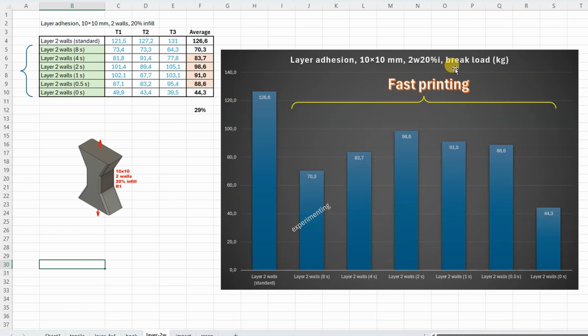Standard speed, fast printing, and I already mentioned that this 8-second version was experimental printing, playing with parameters. Now I'm not sure, only this one doesn't really fit into this picture, the 4-second version. Maybe he was still experimenting with the parameters, I'm not sure, but after this more or less constant values, and only here I could measure some weakness in the layer adhesion, probably because of some small under extrusion.